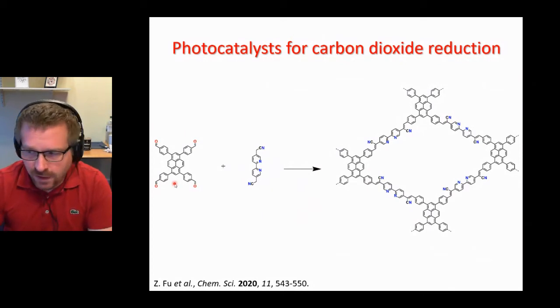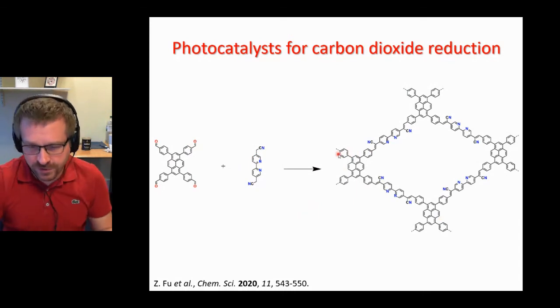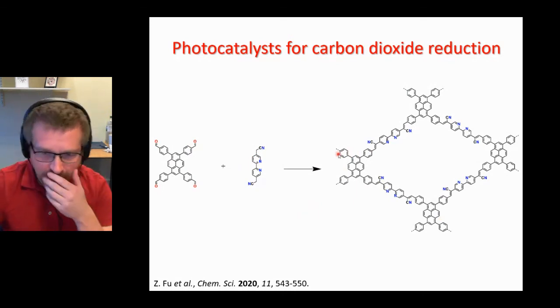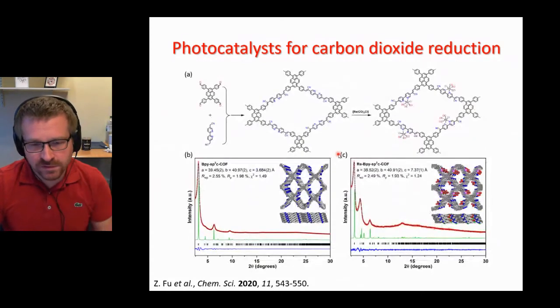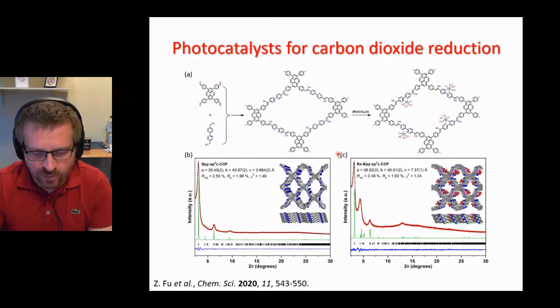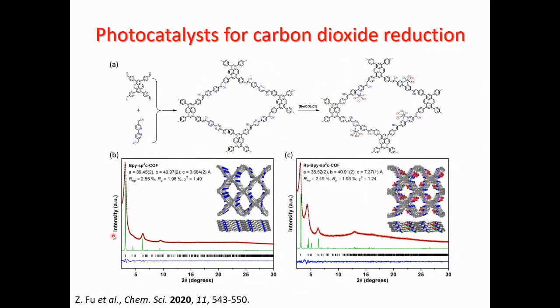In this case, we looked at so-called covalent organic frameworks. These can be made using low temperature condensation reactions. You can see here this condensation reaction between this aldehyde and this alpha cyano compound, producing a link between the two units, and then it can condense into a larger structure of increasing complexity. These materials are formed in really high crystallinity as well, as you can see here at the bottom from the XRD spectra. So they have some order to them. And then looking at the models here, you can see that we have a stacking of layers, which agrees quite well with the crystallinity, with the XRDs here as well.